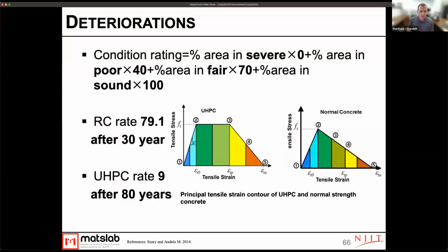We also looked at a condition rating system to look at the condition rating at different time periods. This figure isn't showing correctly, but the reinforced concrete was at a condition rating of basically 79, whereas the UHPC was up in the 90s. So it had only deteriorated about 8%, whereas the reinforced concrete deteriorated significantly more.